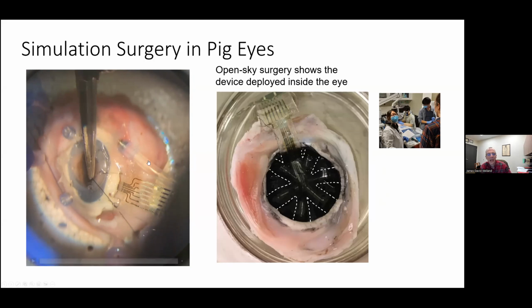And there it is. And so after he completed this, he cut the top of the eye off. And it's hard to see, but we've traced out the edges of the array. So the array, in fact, did unfold in the eye. So obviously a long way to go with this, but we've fabricated a device that has multiple materials. It uses a hydrogel approach to unfold in the eye. So it has a functional polymer, and that hydrogel does not seem to compromise the electrical properties of the array in a way that would prevent current from reaching the retina. So we think this is a good approach to achieving peripheral vision.